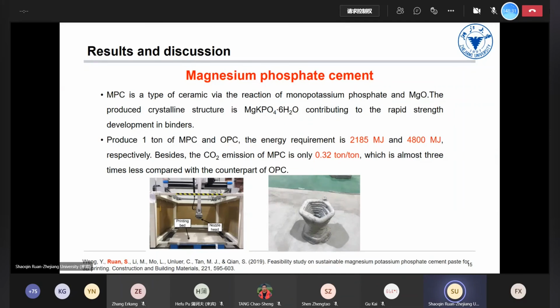To produce 1 ton of MPC versus OPC, the energy requirement is quite different, and the energy requirement of MPC is much lower compared with that of OPC. The carbon dioxide emission of MPC is also only about 0.32 ton to produce 1 ton of MPC, which is almost 3 times less than that of OPC.